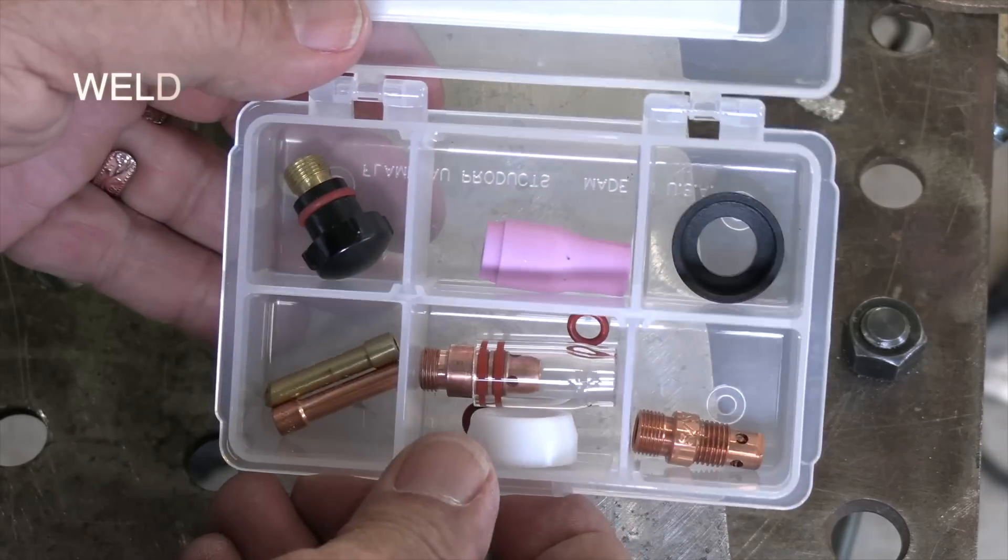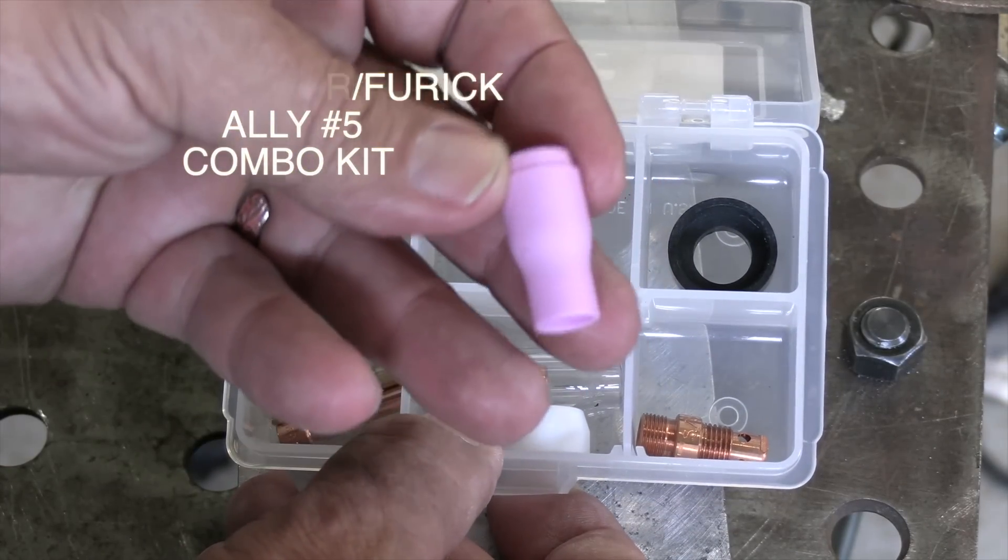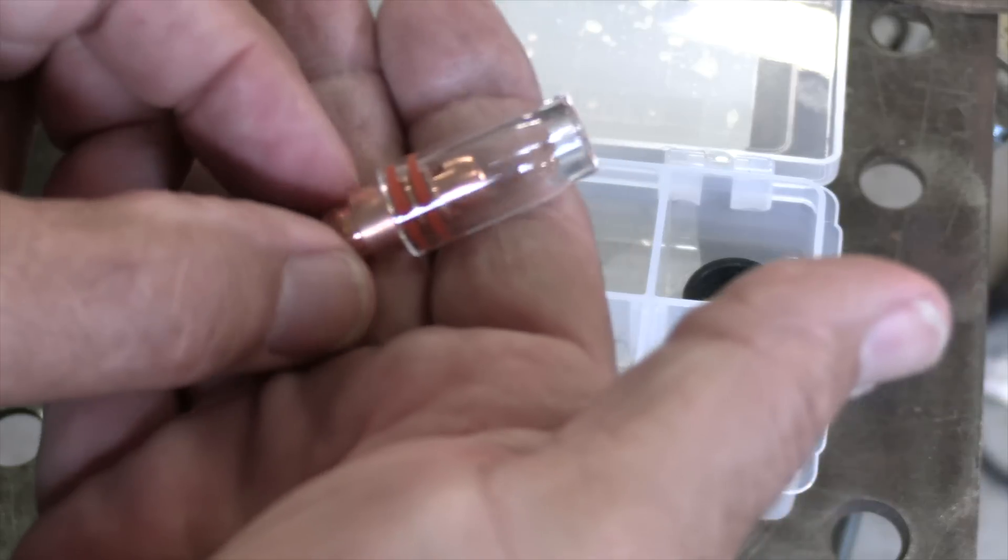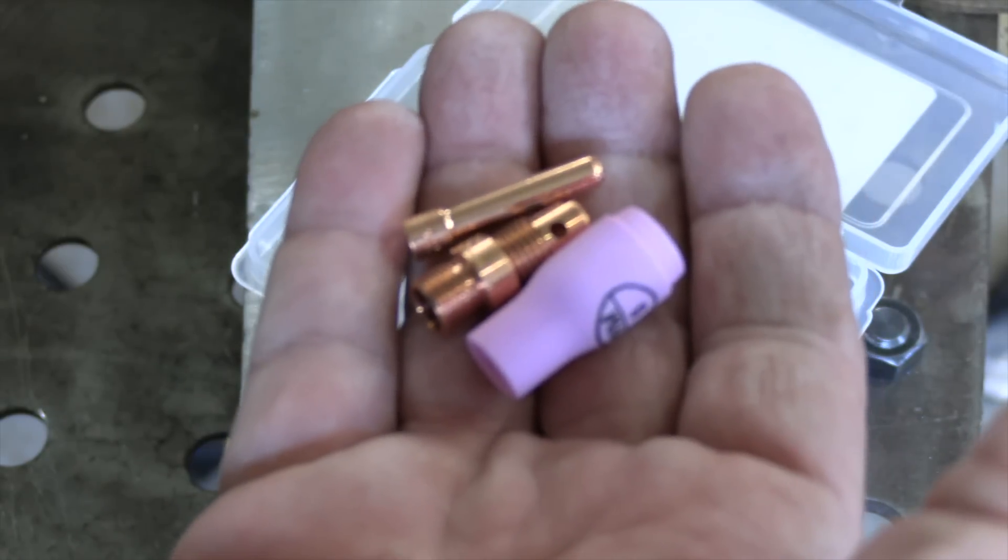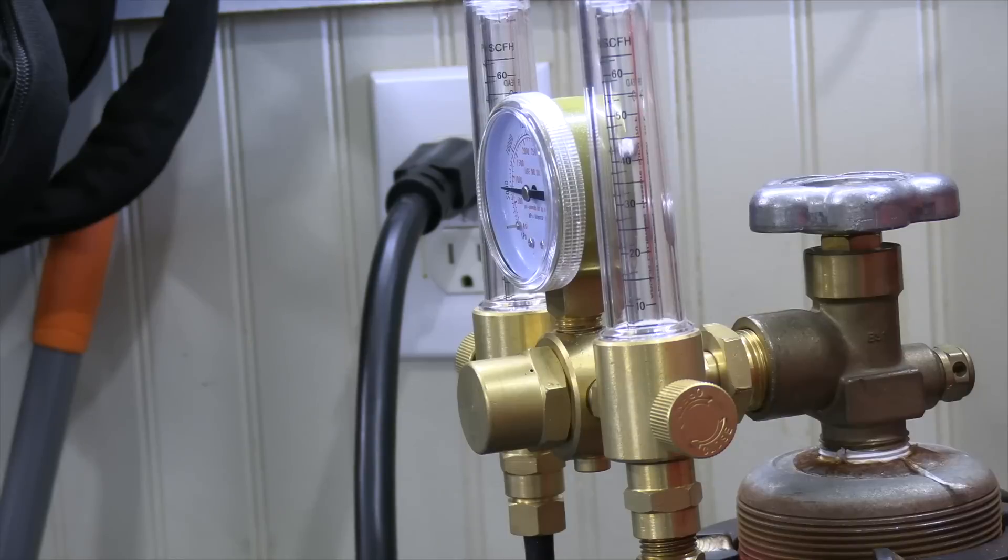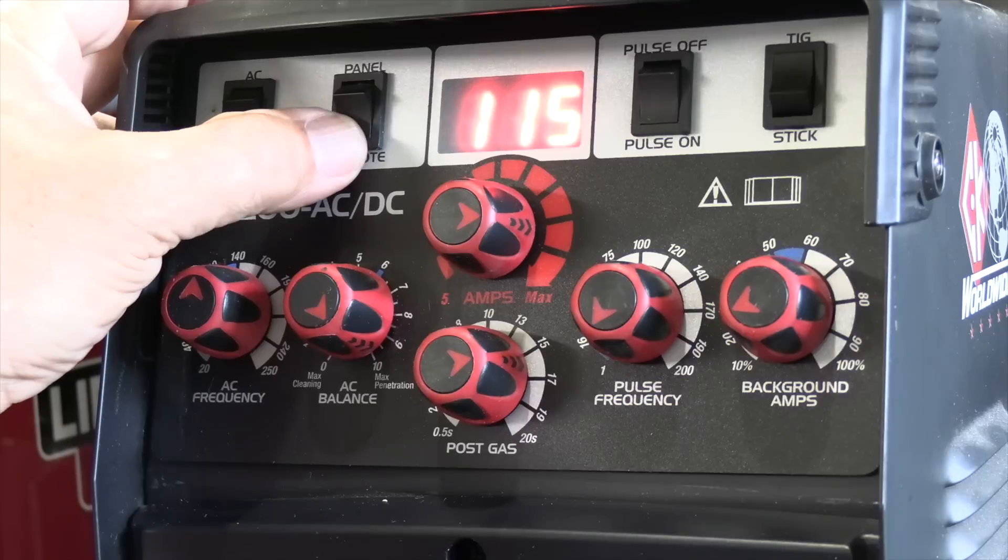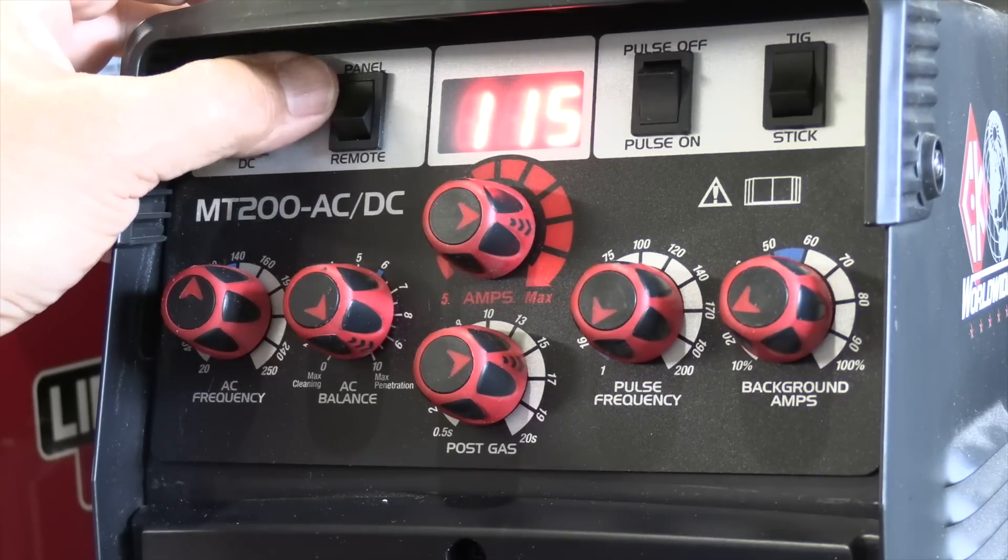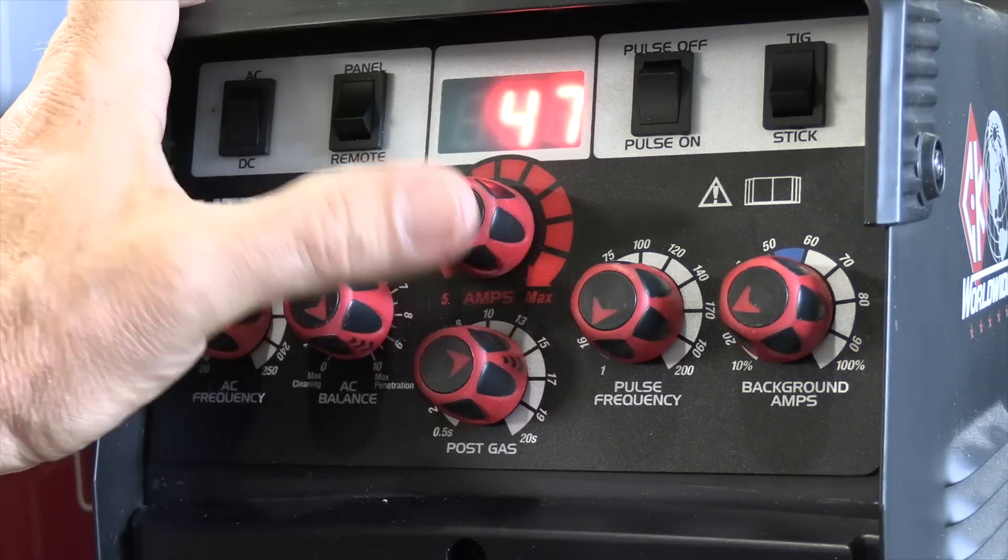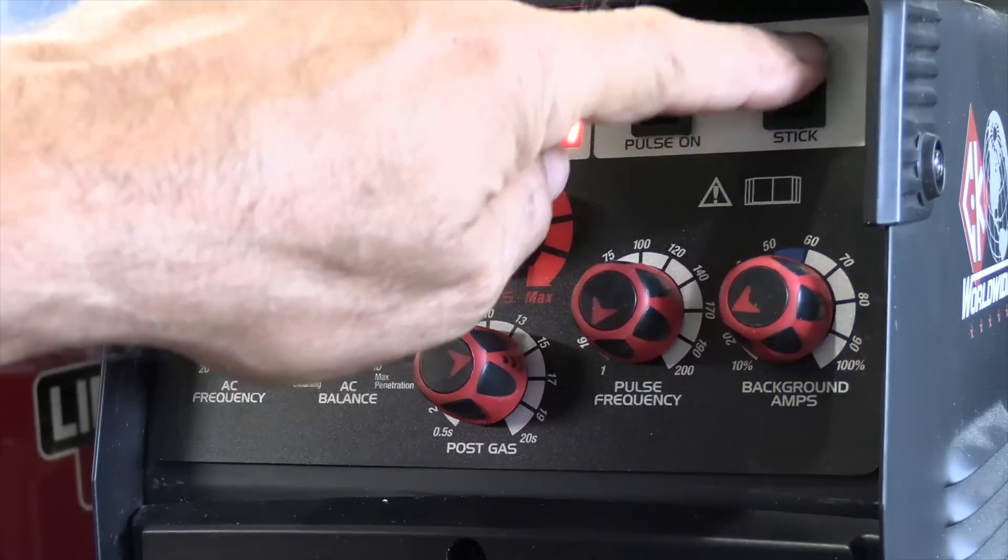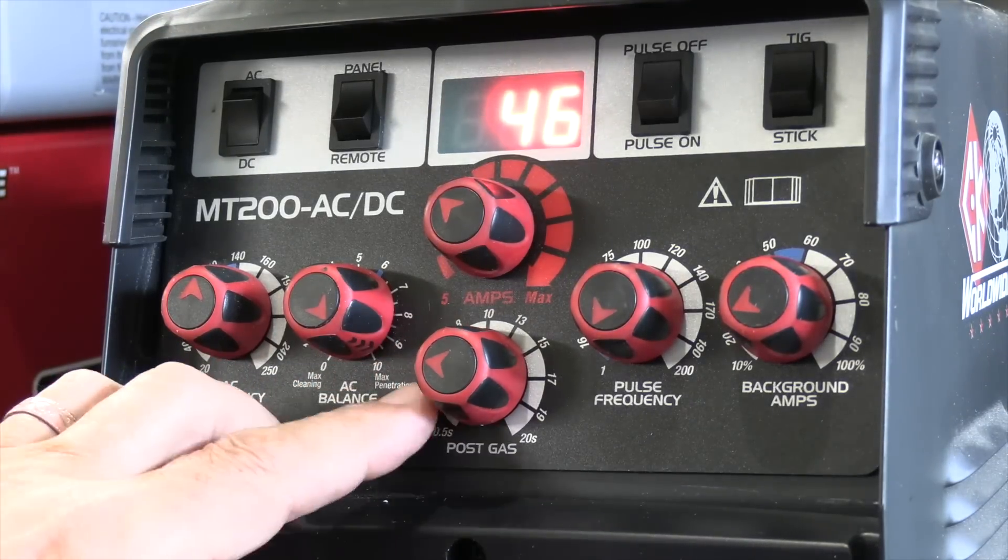I'm going to grab the number five ceramic cup out of this combo kit. It's got a ceramic as well as a clear cup. I'm putting the five on because that's what I would use if I wanted to save gas making a bunch of tacks. With the ceramic cup I'll be able to prop without slipping and I'll only need about 10 CFH of gas. I'm running off the wall here, 115 volt on this little machine. I'm going down to 10 CFH. Now here's the trick: this machine has a panel and remote switch. A lot of machines do. The panel means I basically turn the foot pedal into an on-off switch, so whatever I have set on the panel, that's the amperage I get, and it works great for doing burst tacks, also called flash tacks.